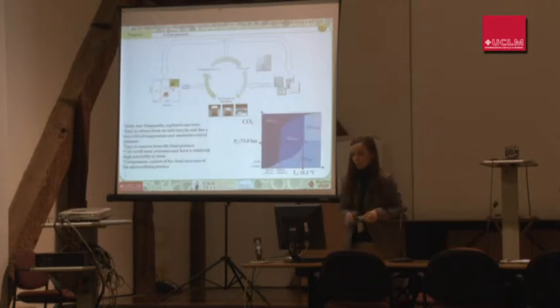Once the solution has been prepared, we propose the use of carbon dioxide to remove the solvent instead of the traditional vacuum or distillation. We decided to use carbon dioxide because it's inert, non-flammable, non-explosive, and non-toxic. It's very easy to obtain from the air. It presents a very low critical temperature and a moderate critical pressure. It's very easy to remove from the final product, can swell most polymers, and also allows tuning the final structure of the microcellular plastic.